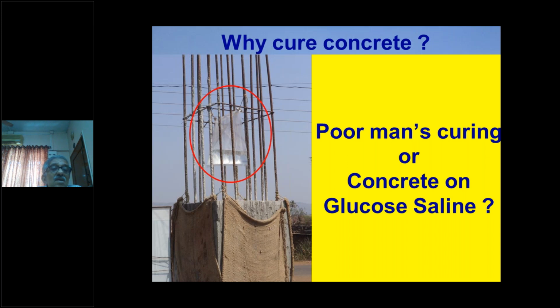Again, here too, there is no drop of water falling. The hessian is dry and it's not going to protect your concrete or cure your concrete. So these sorts of methods are not permitted or not allowed. You have to do proper curing continuously for 7 days, day and night.